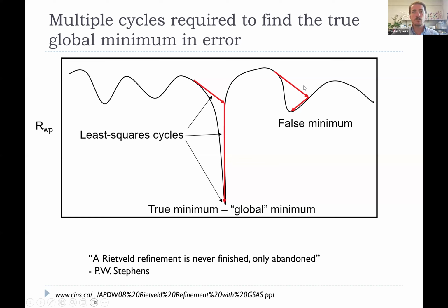There are also things in the software itself that can try and minimize getting stuck. For example, you can take bigger or smaller jumps along the x-axis here, which represents how much you're willing to change your parameters at a time. Changing the values a lot, taking big steps, is more likely to find the global minimum, but it's also more likely to do what's called diverge. In an ideal scenario, you would be making small changes, but continually getting lower and lower until you find a minimum.